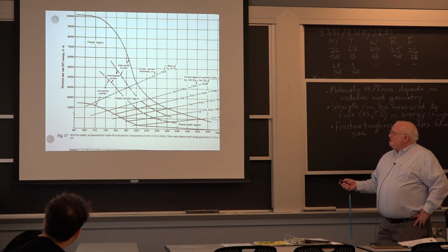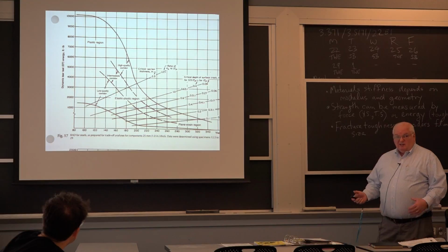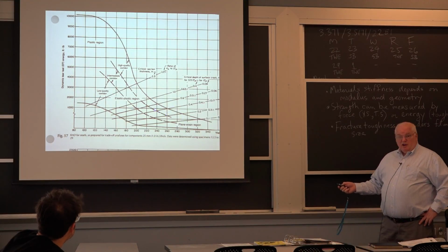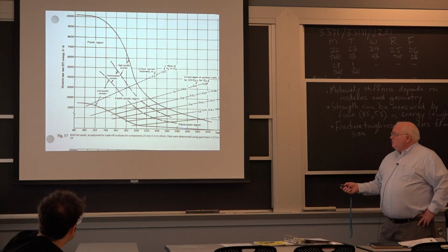And this is the plastic region up here, lots of toughness in low strength steels. This is 100 KSI tensile strength. You get up, and this is the plastic region where you're ductile. You get up here to very high strength, 300 KSI. Now this is the strength of aircraft landing gear, okay? You folks from Boeing, okay? This is where the landing gear are, 280, 300 KSI. It's what we call the plane strain region.